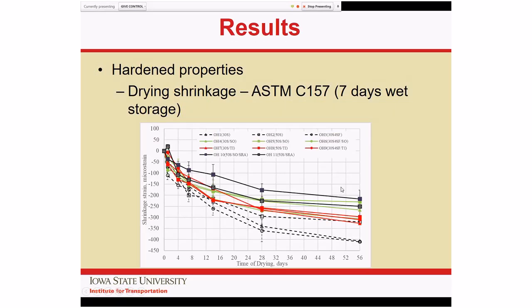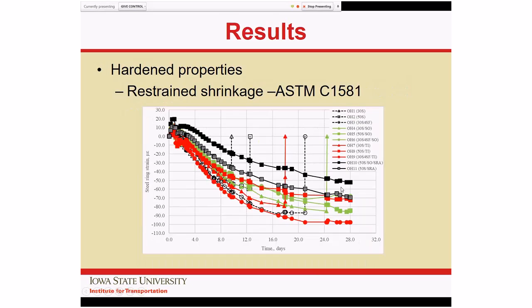These are the drying shrinkage, the C157 prism tests. These are the data from the rings, and you can see that several of them did indeed crack. The ones that jump up is where the system cracks, and you get a sudden drop in the stress. But again, very similar results: the slag systems do better, the lightweight internally cured systems do better, and the shrinkage reducing admixture systems do very well.